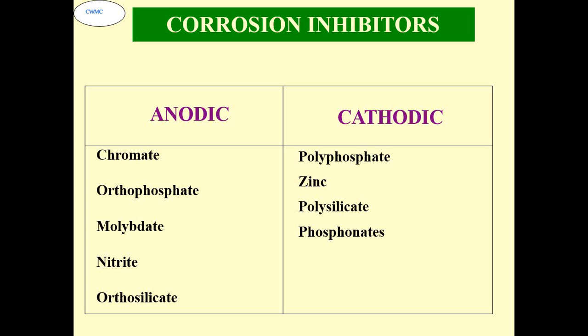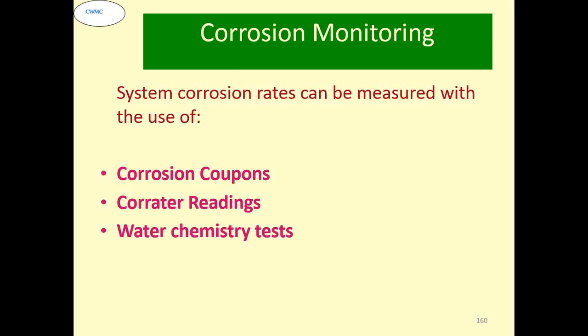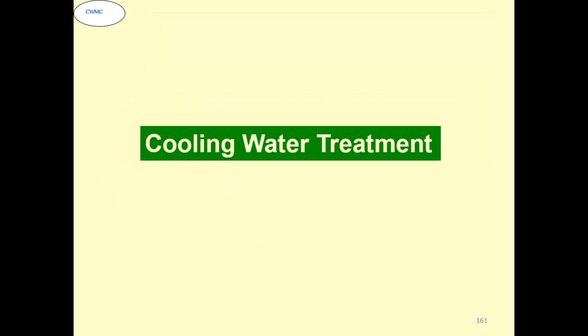So the anodic type of these things are chromate, orthophosphate, molybdate, nitrite, orthosilicate. Orthosilicate is again considered suitable even for drinking water. Phosphate is again suited for drinking water where normal limit is about 5 ppm. Polyphosphate, zinc, polysilicate, polyphosphonates, they are all cathodic inhibitors. Monitoring can be done through corrosion coupons, Corrater Readings, or water chemistry test.